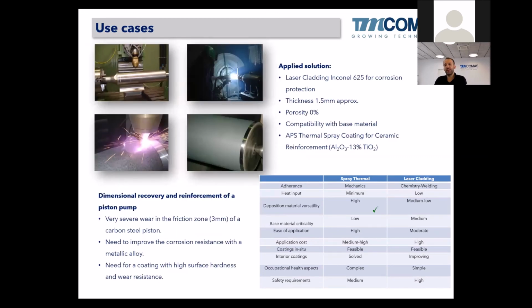And this is the last, I think it's the last slide. In this case, we have used both processes, thermal spray and laser, to recover the same part. The customer has a piston pump which works with some pistons, and in that case there was a severe wear in the friction zone of the piston, about 3 millimeters, and it was a carbon steel piston, and also they had some corrosion underneath.